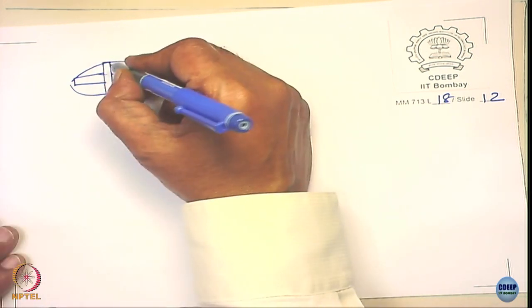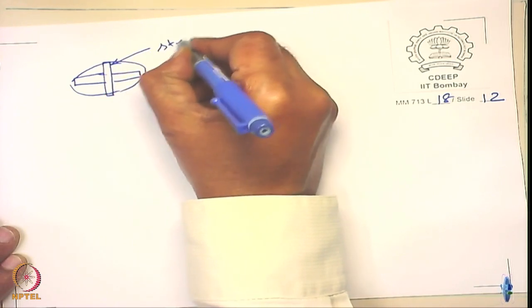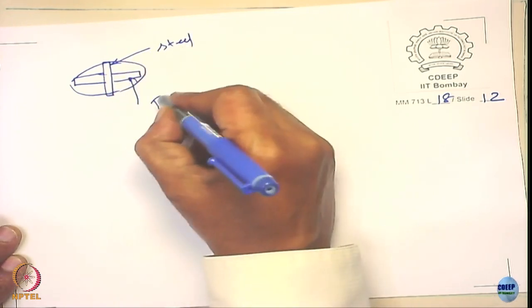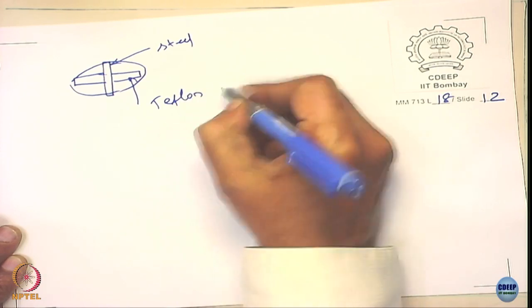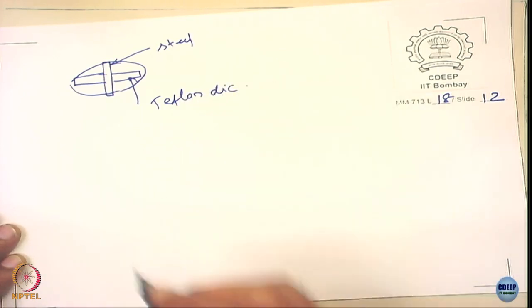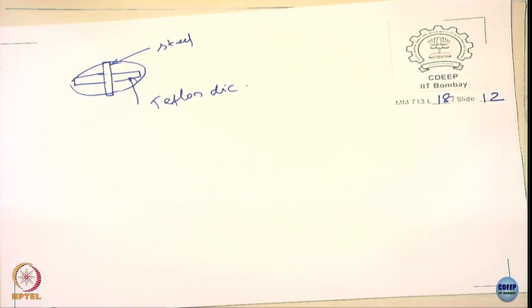This is the steel, and this is your Teflon disc. So, immerse in ferric chloride solution at the temperature of your own interest, and measure after 72 hours, see what happens, if there is corrosion or not. If there is no corrosion, that means at that temperature, the material is resistant to crevice corrosion.